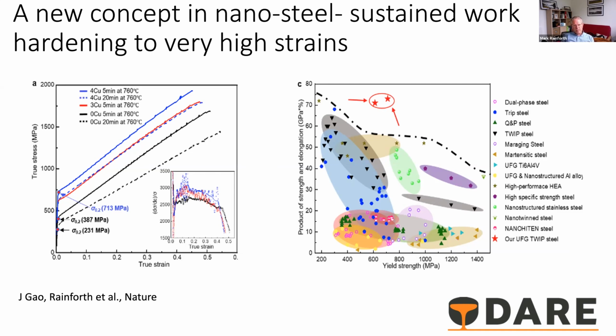So you can see from the curve there, sustained linear work hardening up to a true strain of about 0.45. So we get this massive ductility, taking the material strength up to just shy of 2 gigapascals. And one might say, well, how do you manage to get such high ductility in an alloy that's basically precipitation hardened? Because if you look at all precipitation hardened steels, indeed like the previous example I gave, then you do not get this high ductility.